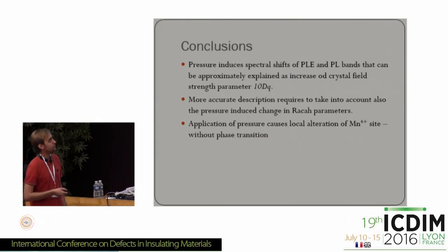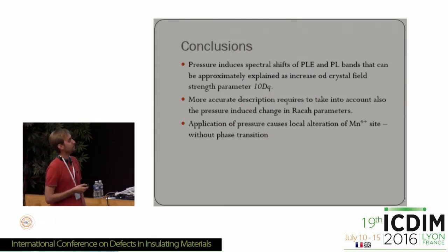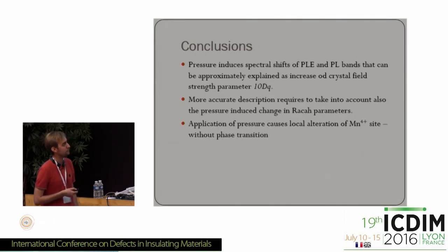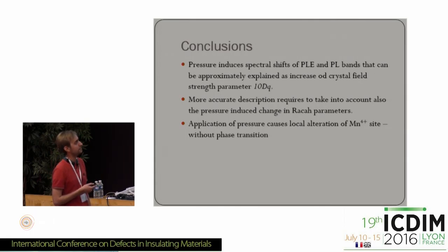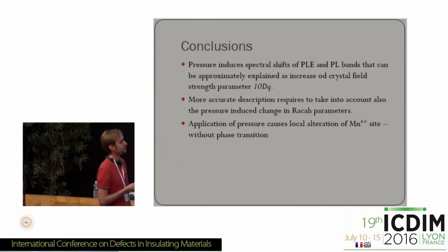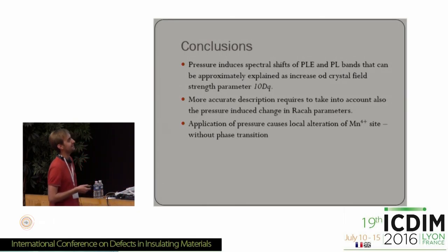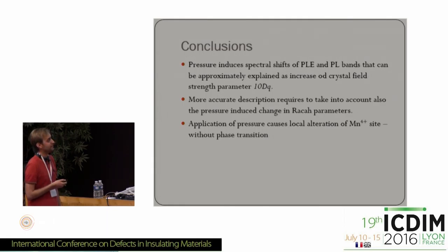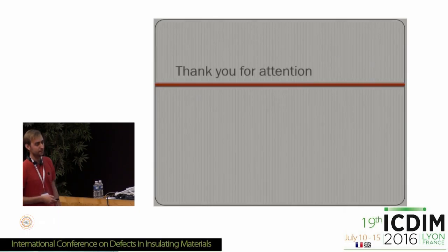Our conclusions are: pressure induces spectral shifts of excitation and emission spectra that can only be approximately explained as an increase of the crystal field strength parameter. More accurate descriptions require also the other parameters present in the theory. Additionally, the application of pressure causes local alterations of the manganese 4+ site without inducing full phase transitions. Thank you very much.